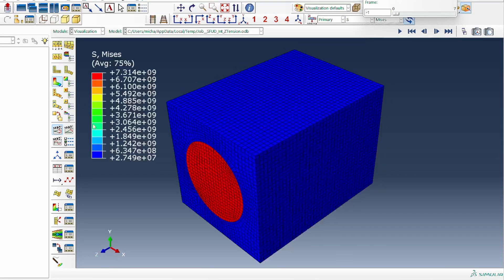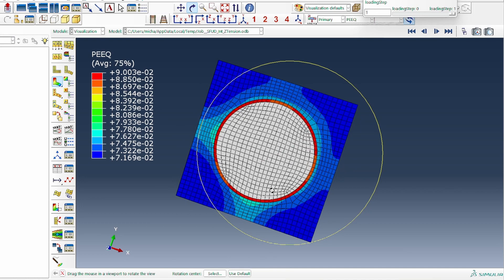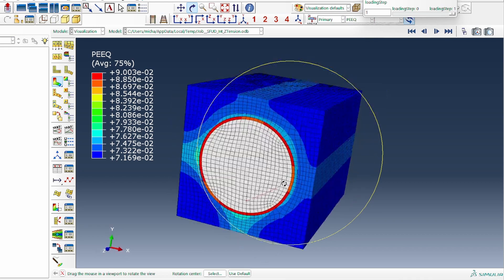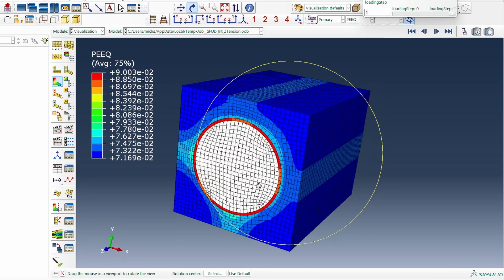With z-tension, the body is pulled along the fiber axis and the fiber takes most of the loading. Going into the plastic regime shows the interface has failed plastically, as expected. This demonstrates why in composite materials the interface is typically the weakest part — most failure is triggered at the interface. Note that a smaller interface region was used compared to the original model.